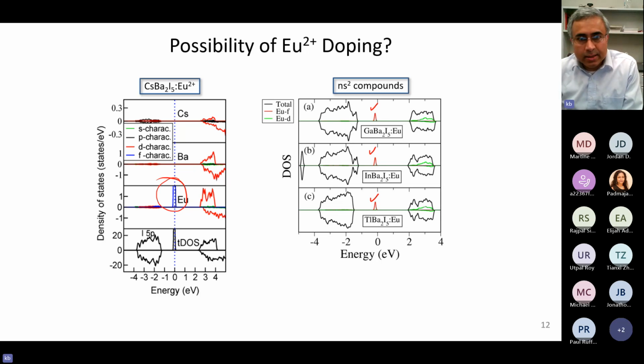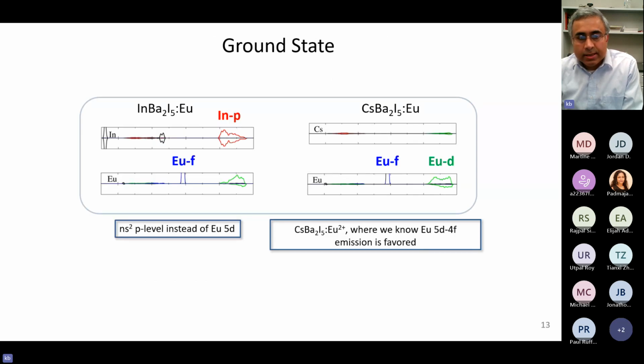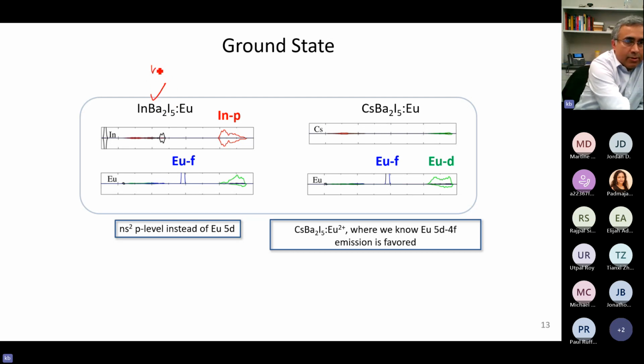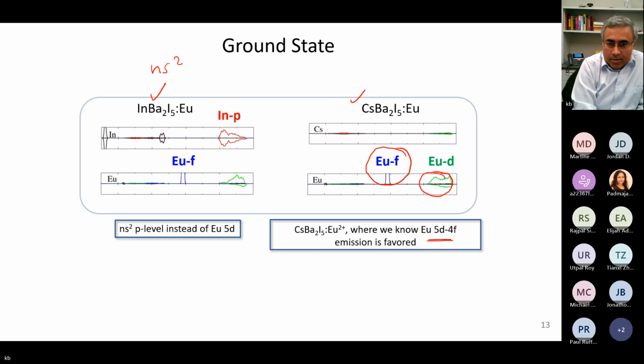However, there is some difference also. The difference I'll point out in this example on this slide. Let's take indium barium iodide as an example of Ns2 compound, and this is cesium barium iodide. In cesium barium iodide, you see you have europium F state right there in the middle of the gap, europium D near the bottom of the conduction band. And that is exactly the scenario we need for europium 5d-4f emission, which is true in case of cesium barium iodide.